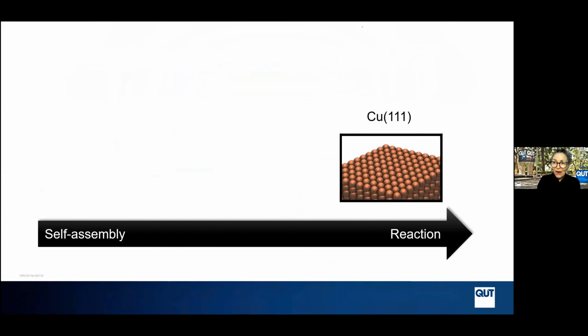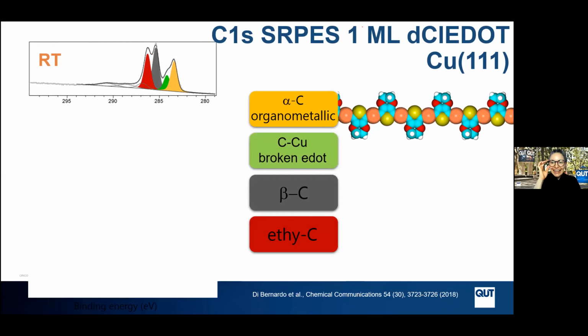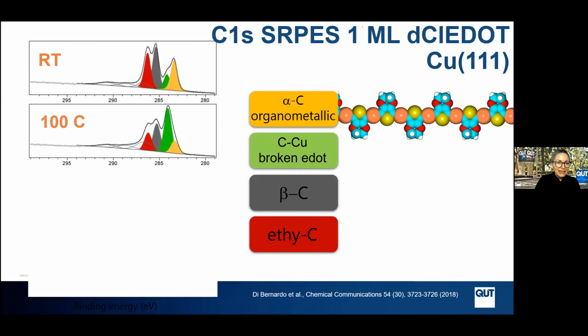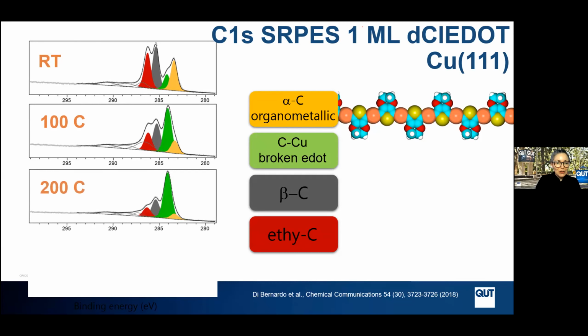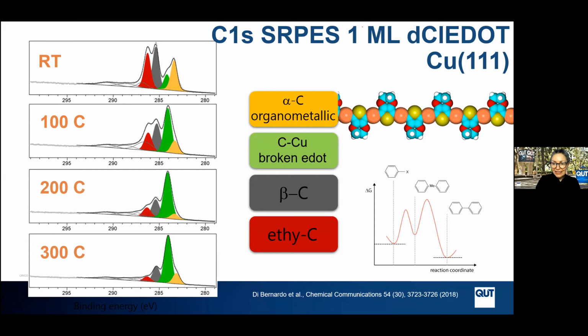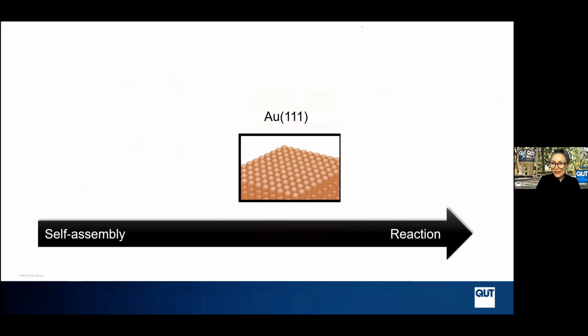So working on copper, and this is where I'll start going quickly because I think this was part of my talk last time I was at Monash. Working on copper, immediately upon deposition, we see the green peak, which is indicative of broken molecule. And so even without heating, already we know the substrate's too reactive. Adding temperature only makes it worse. The molecule is irrevocably broken. This is not the substrate we were looking for.